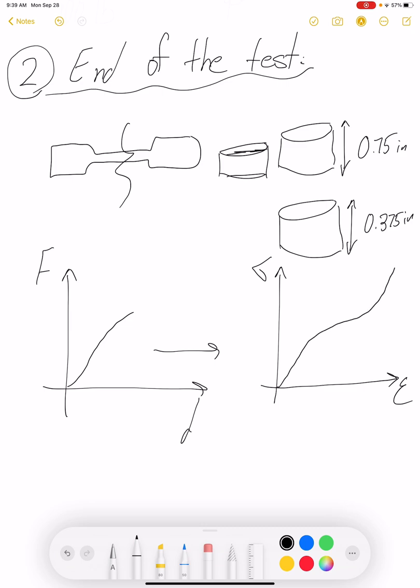But one distinction is that you are not going to see a drop in stresses similar to tensile testing, because after some point the machine is compressing against itself. So here our stress-strain curve does not represent our material properties but the machine properties against itself. So it's very important to cut our data here whenever the slope is changing. Sometimes it's very difficult to report ultimate compression because of that reason.